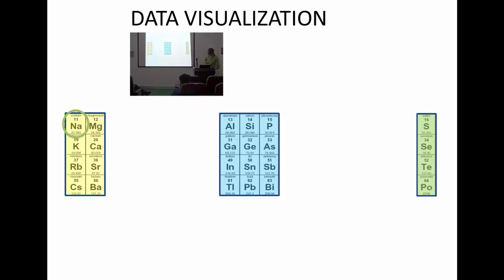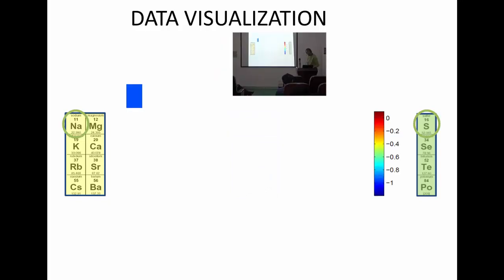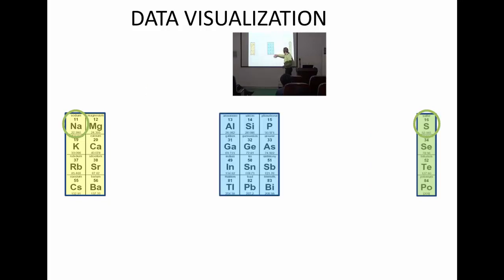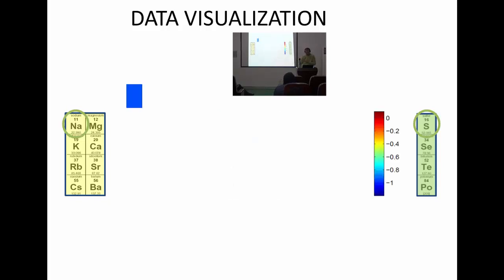So we keep working just with these three blocks. I will take as an example all the ones that have sodium in the first place and combined with, in the last place, sulfur. So we forget about the middle block for a while. So I have sodium at place 1, sulfur at place 4, and now in the middle I have two elements I have to choose from this 3x3 block that you have here. So we have 12 times 12, 144 different crystals that both have sodium and sulfur. For these 144 different crystals, we calculate the elemental formation energy, and I take the lowest one of these. And the lowest one of these, I put in that square here. So this blue color code reads from this temperature bar what is the elemental formation energy of the most optimal crystal in that set of 144.